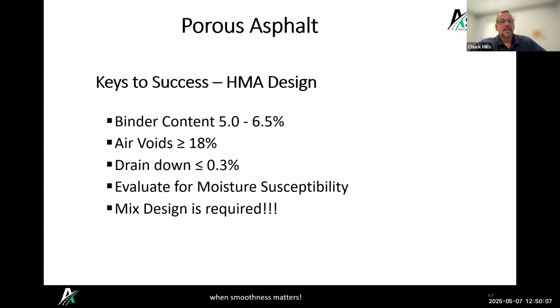So keys to success, here it is. The binder content is typically 5 to 6.5%. Air voids greater than 18%. Drain down less than 0.3%. You want to evaluate for moisture susceptibility. A mix design is required.